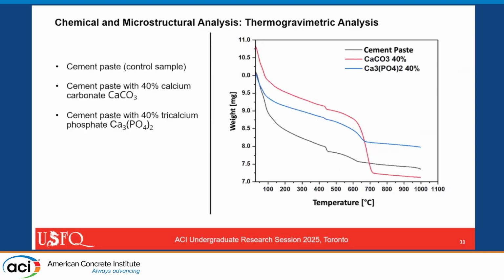Okay, so in the methodology, we also wanted to analyze the content of these mixes, and we used thermogravimetric analysis in 3 different samples. The first one is the cement paste, that is the control sample. Then the second one with 40% replacement of calcium carbonate, and the third one with tricalcium phosphate.